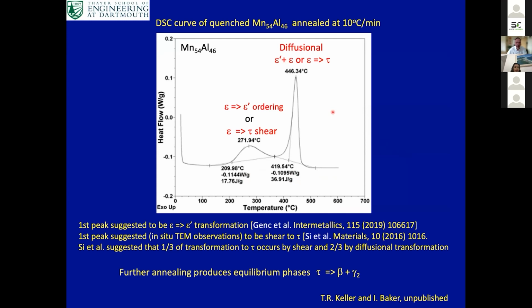This is simply for manganese 54, aluminum 46. And you can see in this case, in this calorimetry curve, this low temperature peak is a little bit more prominent. It's not quite clear whether this low temperature peak is really this epsilon to epsilon dash ordering transformation, or epsilon to tau by shear transformation. There's been two different suggestions about what this is. But at high temperature, again, you get this peak, which is either the epsilon or the epsilon prime plus epsilon transform into the tau phase by a diffusional transformation.